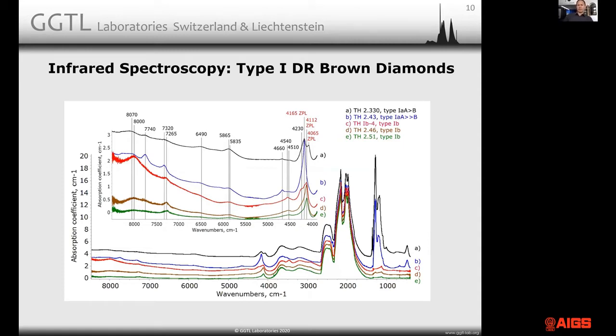Here you can see a range of what you see in type 1B diamonds and in type 1A diamonds. There are basically 3 different zero phonon lines visible at room temperature, 4165, 4112, and 4065. 4230, I wasn't sure if that was actually a zero phonon line or not. You'll see later why it's kept as a non-zero phonon line. This center is present in browns, and upon HPHT treatment, almost completely disappears.